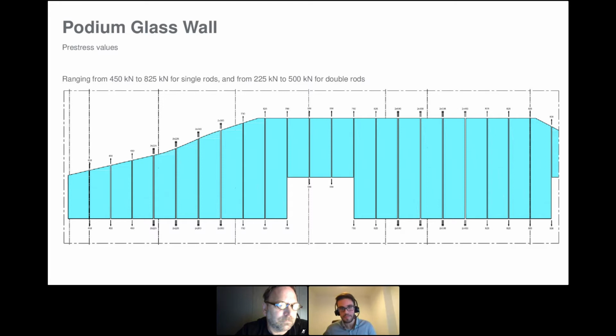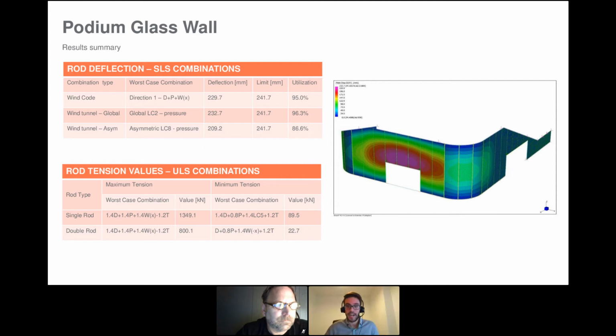We run this nonlinear analysis because of the load case, the wind load case. I think at the end there were roughly 60 serviceability combinations and probably around 120 ULS combinations, because we also had to consider different levels of pre-stress. The main results were clearly the deflection of the glass panel in the east elevation, which is the most flexible one, reaching around 230 millimeters. So just below the 240 millimeters that represents the height over 60 deflection criteria that we were using.